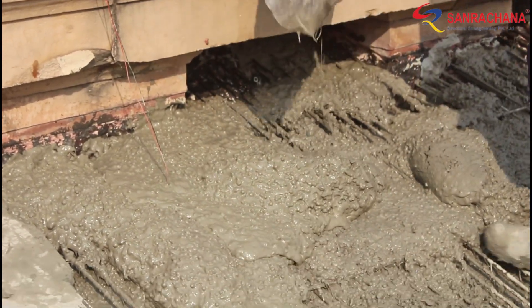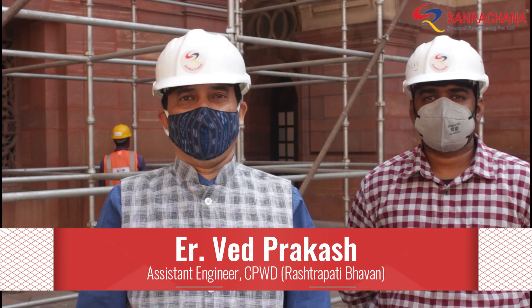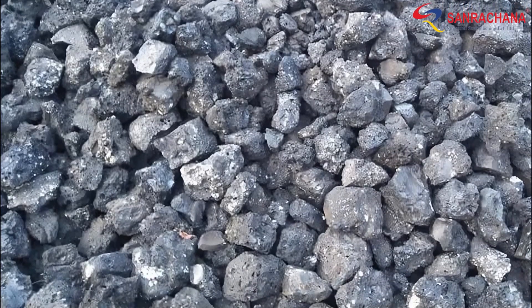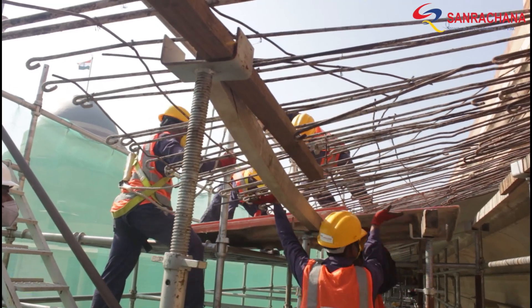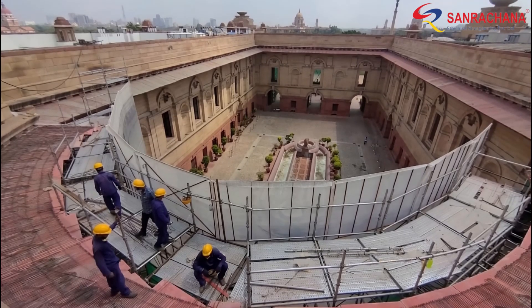And then comes concreting. Structural lightweight concrete is a high-modulus, high-early strength, pre-packaged M25-grade concrete with sintered aggregates, which is ideal for dead load reduction of the 2-metre cantilevering reinforced chhajjas. This job had to be repeated countless times in a piecewise manner since the work front availability was constantly hampered. Sanrachana handled the job with utmost professionalism and adhered to all the safety protocols like VIP movements, COVID, etc., which were imposed from time to time.